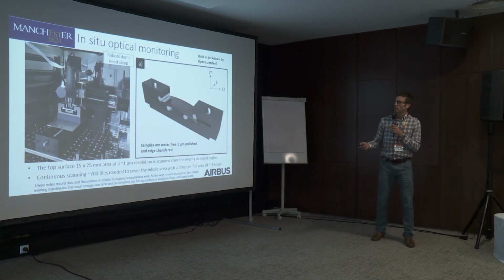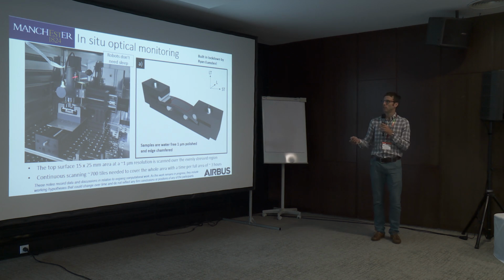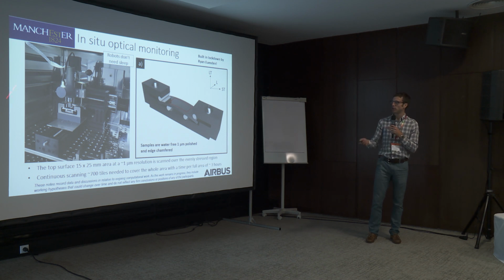And what we've done, I was very happy that my PhD student Ryan Euesden spent most of his lockdown in COVID building this in situ scanning optical microscope, which we've then put inside a humidity cabinet, and it basically scans across the surface of a standalone 4-point bend specimen. So here's our specimen. It's 15 millimeters across, and we can scan this area 15 by 25.